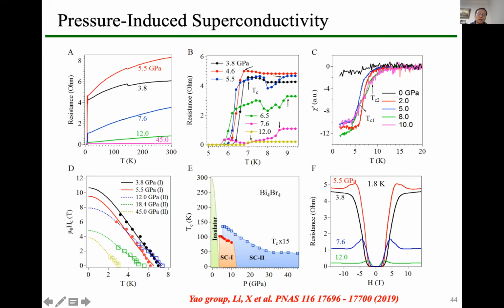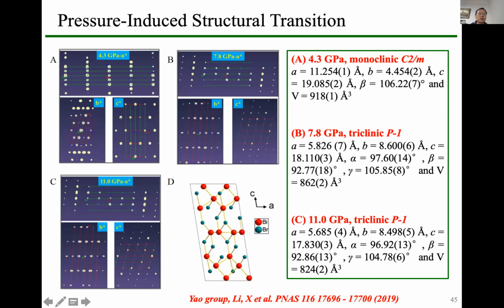But because the crystal structure is maintained in between this region, it is possible that this material might be a TI and also a superconductor in this region. So it means that this material might be a topological superconductor. So this would be very, very interesting for future exploration. So here is the experiment. We see how the structure evolves under different pressure. For this pressure, it is still like the alpha phase, but for this structure, the crystal structure has already changed, and at higher pressure, the structure is still the same, but the lattice has been compressed.